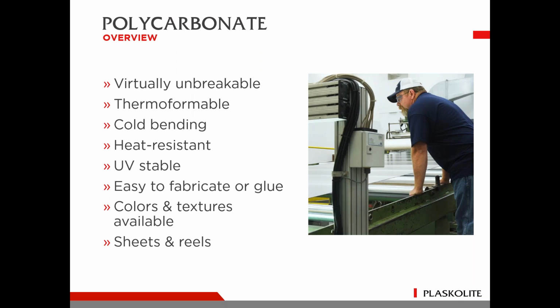So what is polycarbonate really good at? Again, I told you earlier, it's virtually unbreakable. So it's got great impact strength. You can thermoform it. You can cold bend it, so you don't have to put any heat on it. Say if you have a press brake and you want to put a 90-degree angle on it, you can do that through about 1/4 inch. Anything above that, you'd have to put a score behind it to get a good clean bend, but you can do it without putting any heat to it.